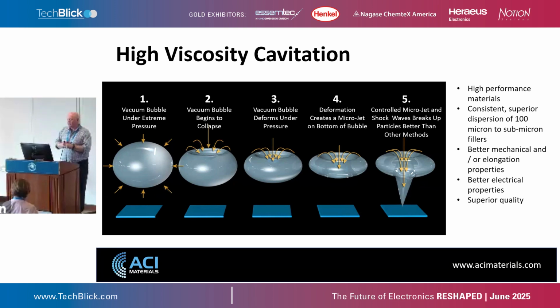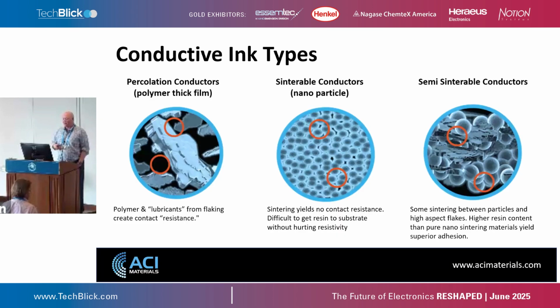And it really gives very high performance coatings, especially with metallic silver flakes and other things, as well as carbon nanotubes, as I said, graphene, and certain pigments and other particles that are difficult to disperse and stabilize. It makes a very stable coating, but most importantly, it gives you the best mechanical properties out of a coating, the best conductivity, and also very consistent quality. This is fully enclosed the way we manufacture, so it makes very consistent products with very high performance.